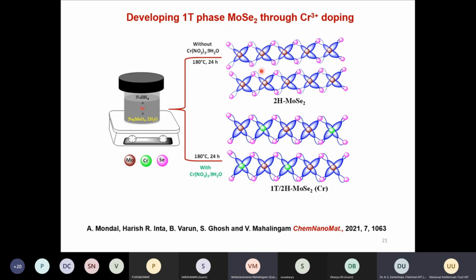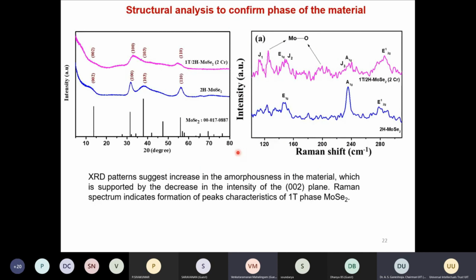Of course, we have done a similar thing on MoS2, but the results were better for the MoSe2. So that's why I'm showing the 1T phase of MoSe2 here. This is again prepared through the hydrothermal method, and we compare the results without and with chromium. Here you can see for the 1T phase and the 2H phase that the 002 plane is basically vanishing. That means the material is more amorphous. Very thin, very few layers of MoSe2 can be obtained by this method.